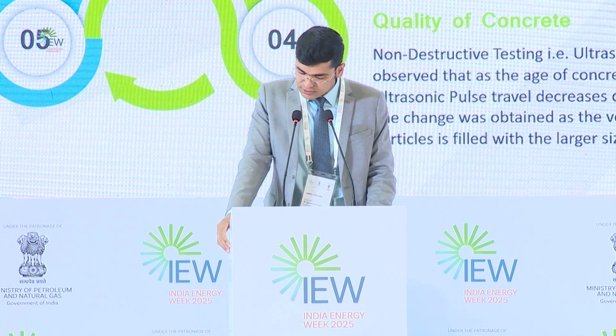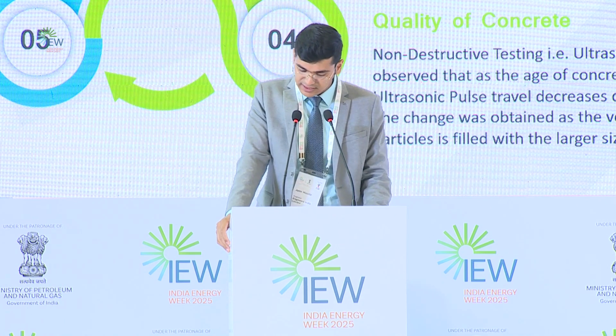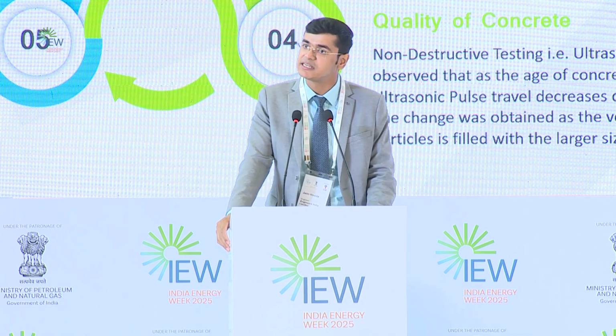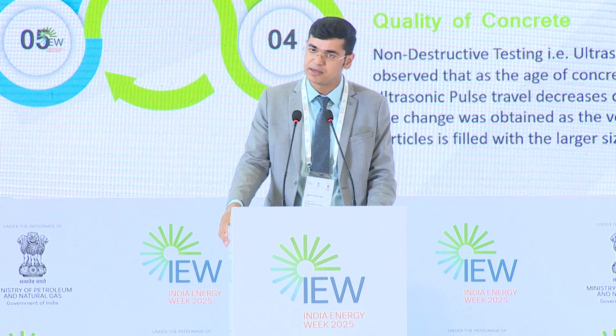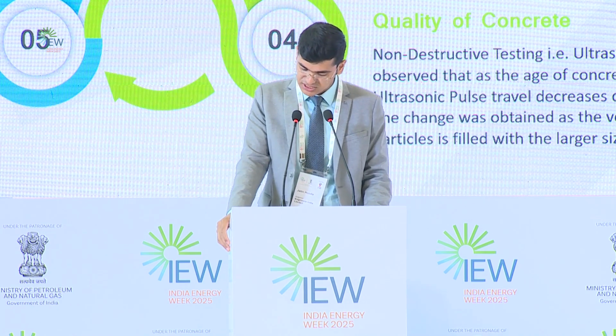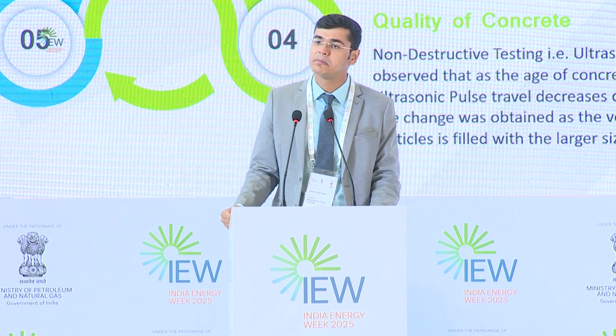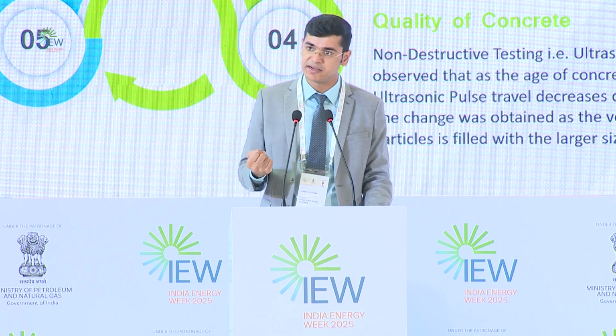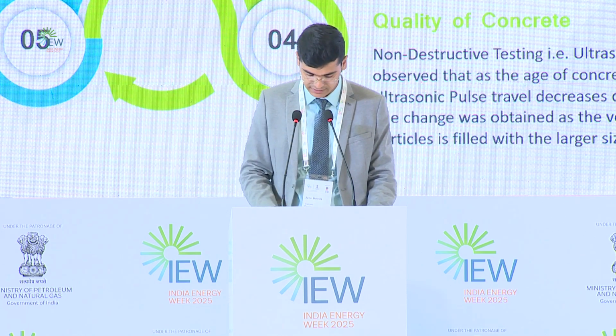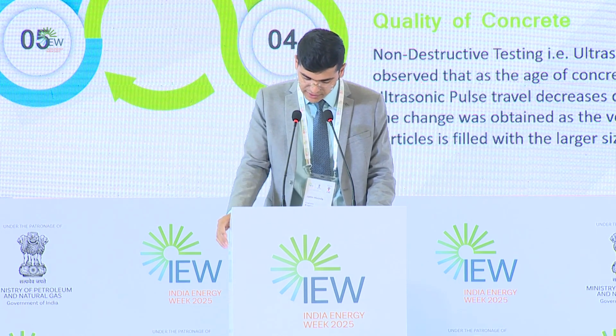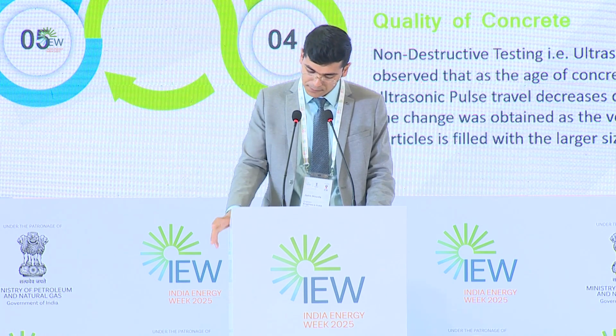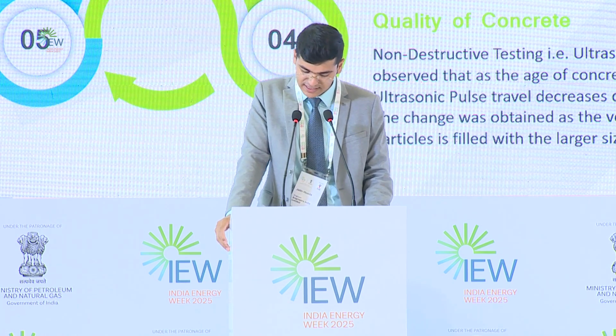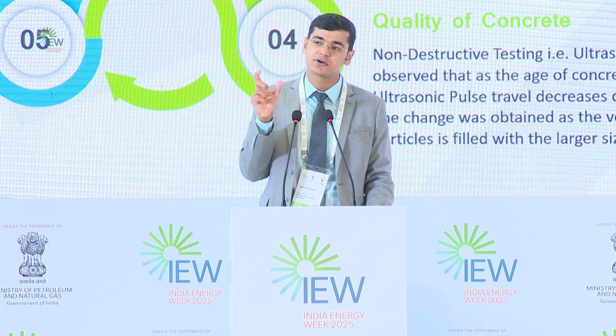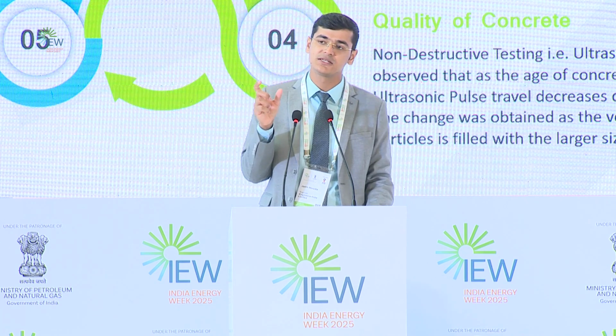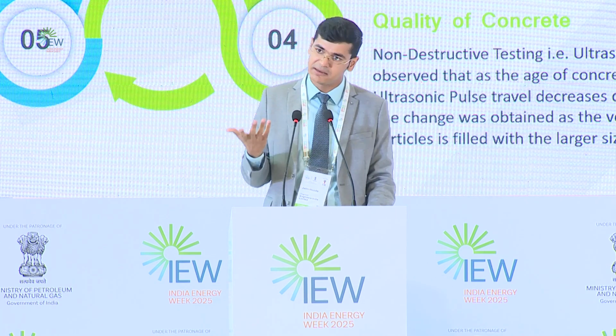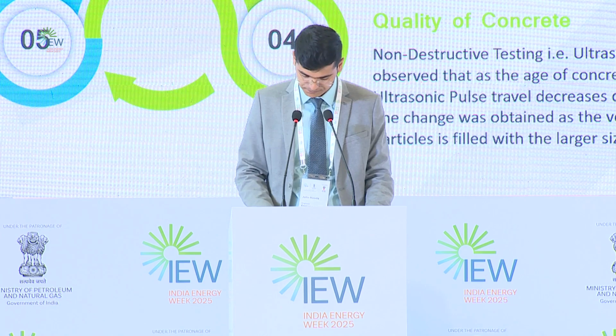In the NDT testing, which is the UPV test, it was observed that as age of concrete increases, the time duration reduces, as you saw in the previous slides, indicating that the material we obtained is a dense material, which is good for construction activity. In the composition of concrete, it was observed that there is an appropriate proportion of CSH gel. CSH gel is the major constituent of Bogue compounds, which is the binding material in the concrete.